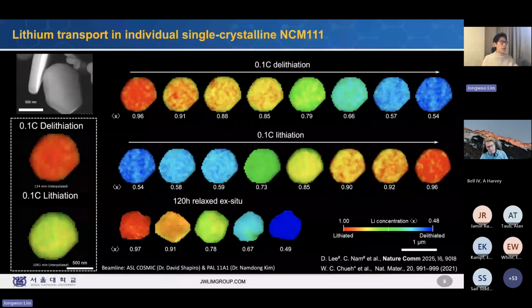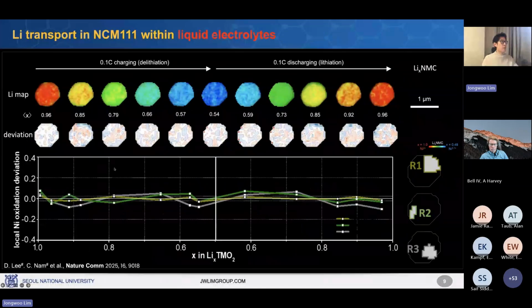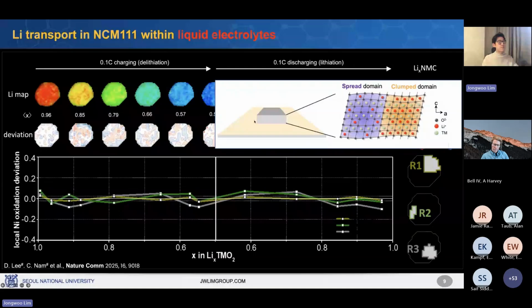And what we're trying to say here is this: maybe the lithium deficient area is actually expanding the c-axis. The lithium rich area is actually shrinking the c-axis. This is actually thermodynamically well known for the NMC particles here. So we are trying to get those kinds of images from this particle. However, we are only looking at lithium concentration at this moment. We are not looking at c-axis or the lattice expansion or shrinkage strain information yet at this point.